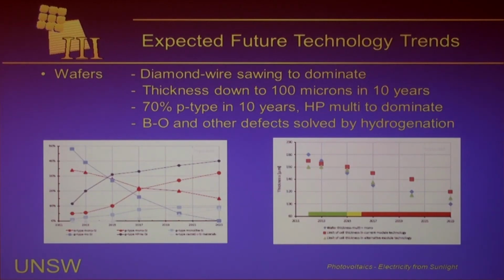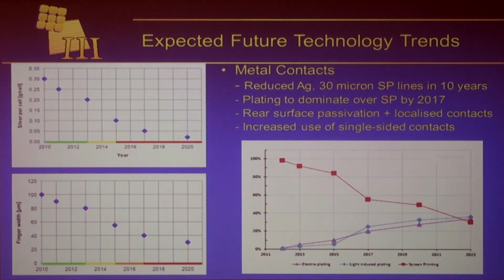Okay, moving on then to metal contacts. Again, I've talked about them somewhat with the evolution from silver to copper. These are the screen-printed silver contacts at the moment, almost at 100%. And yet that's expected to drop down to not much more than 20% by the end of this period here. On the other hand, here we have two types of copper-plated contacts. One of these is electroplated, the other is light-induced plated. But there's a couple of different plating techniques you can use for depositing the metal contacts. Both are expected to grow quite well. Both are expected to take over from silver by the end of this period.